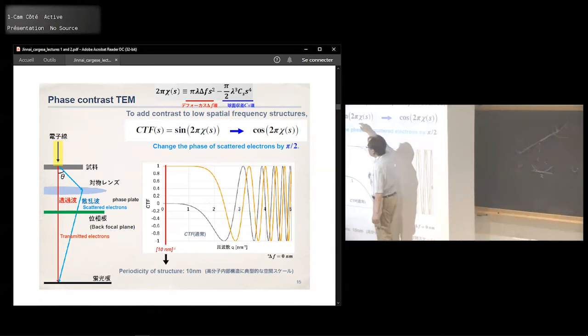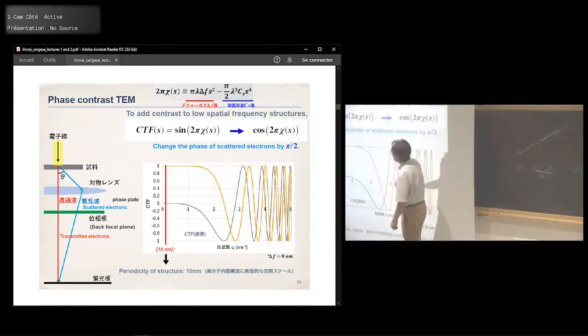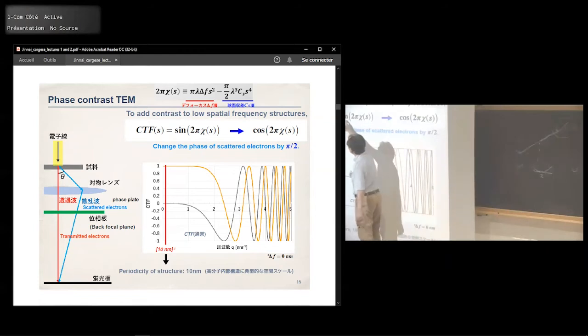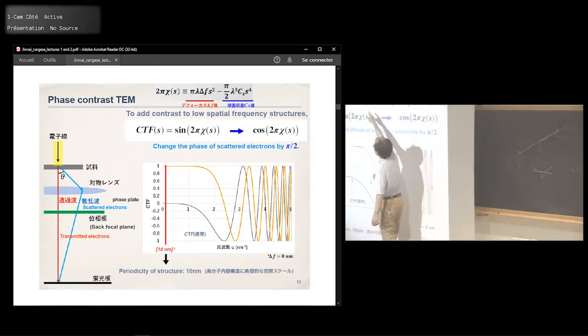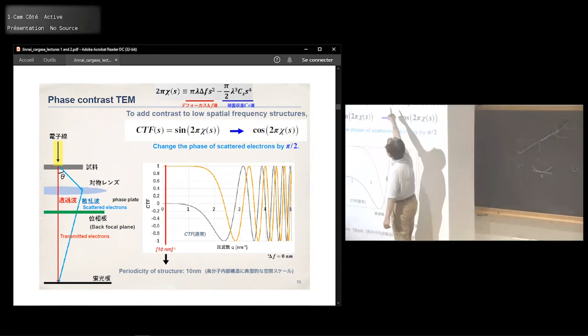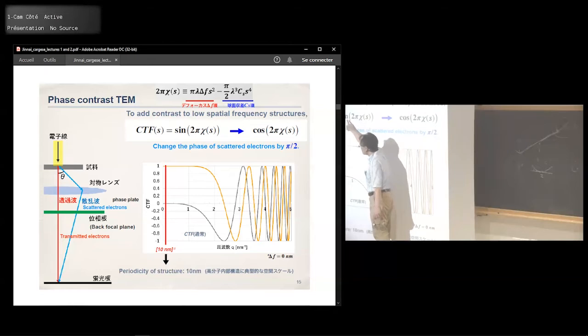So the strength of the phase contrast is given by this contrast transfer function, and this is a sinusoidal function. In here, the first term is the defocusing term, and the second term is the spherical aberration term. As you can see, defocusing and spherical aberration change the phase contrast. But the important thing is that this is sinusoidal.